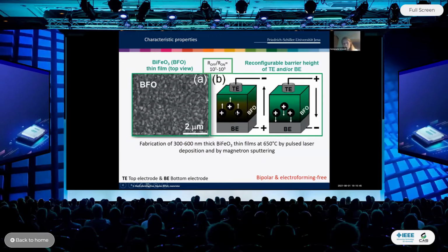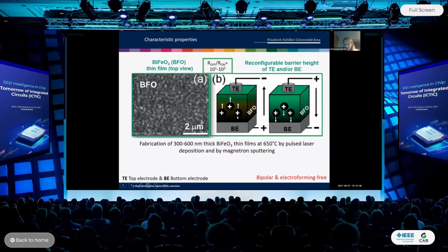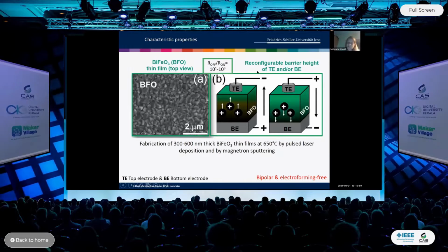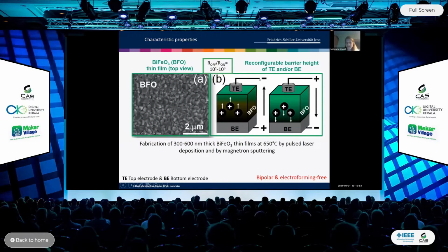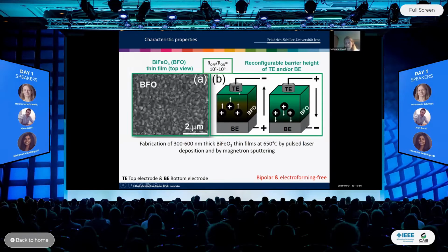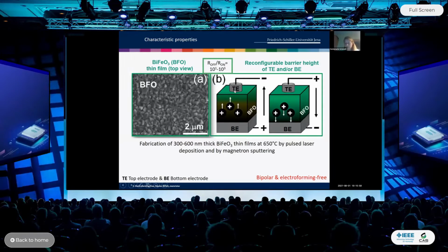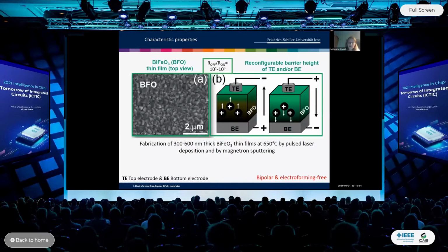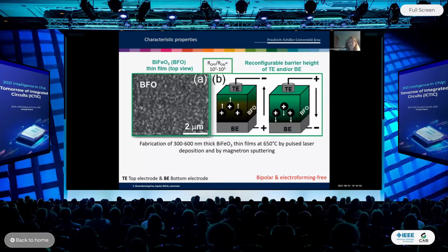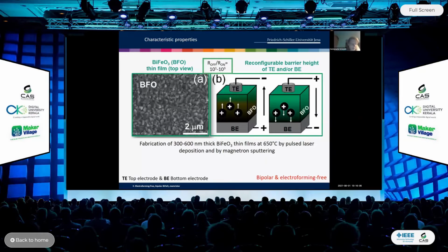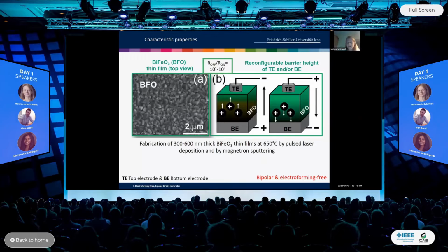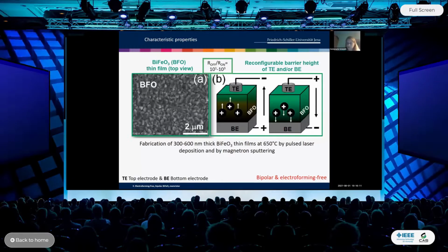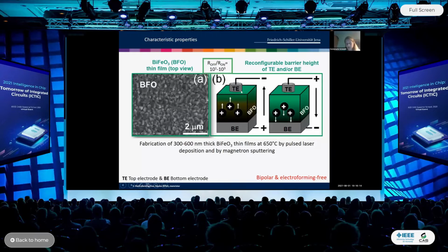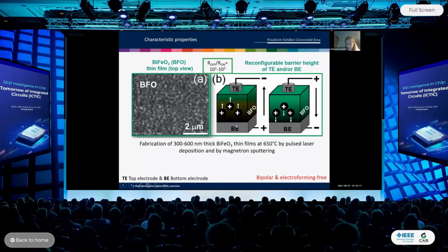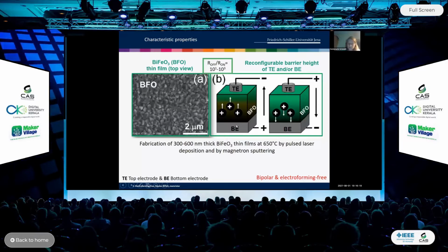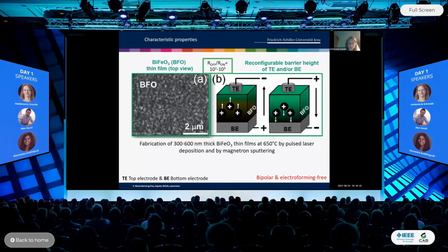That means with the redistribution of oxygen vacancies under application of the writing bias, and depending on the polarity of the writing bias, we can determine which barrier height is reduced and which barrier height is large. And then we can do this in a fine-tuned manner, and I will show you how many applications can be derived from this very nice property. It's not a filamentary switching, it's a switching which depends on the area of the top electrode and of the bottom electrode. And this is very nicely scalable, and it needs no electroforming step.